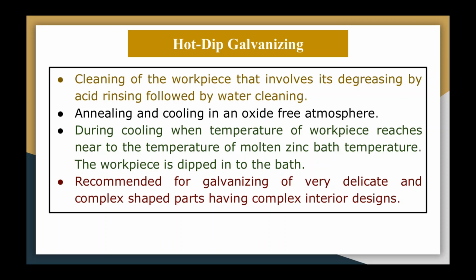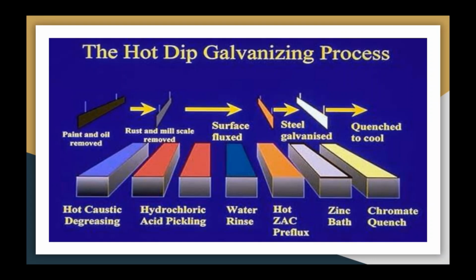And during cooling, when the temperature of the workpiece reaches near the temperature of the molten zinc bath, the workpiece is dipped in the bath. A very thin and uniform coating layer can be maintained by passing the sheet through a roller just after the coating, and this method is not recommended for galvanizing of very delicate and complex shaped parts having complex interior design. So you can consider this a disadvantage of the hot dip galvanizing process. Okay, and here I have shown how one can do the hot dip galvanizing process.